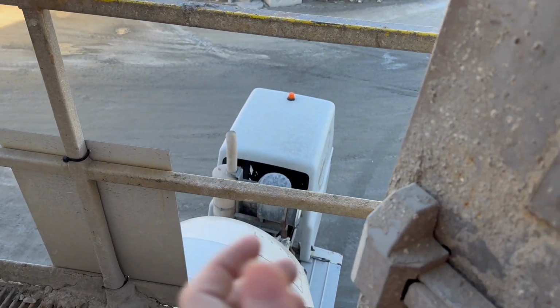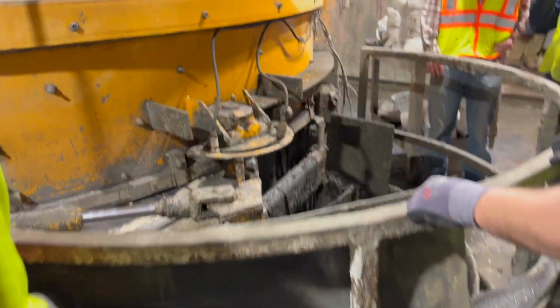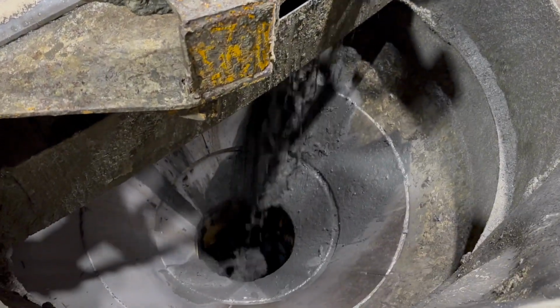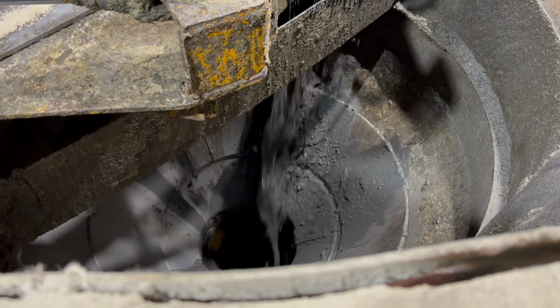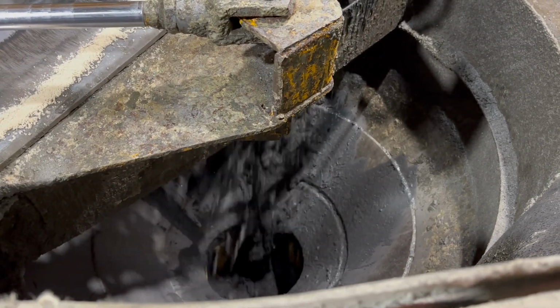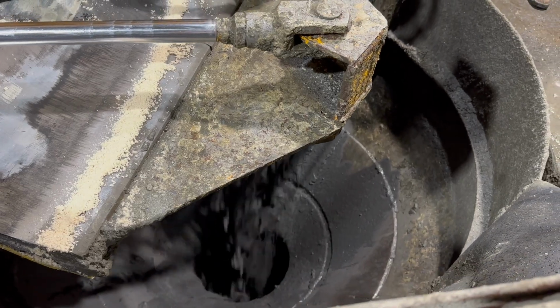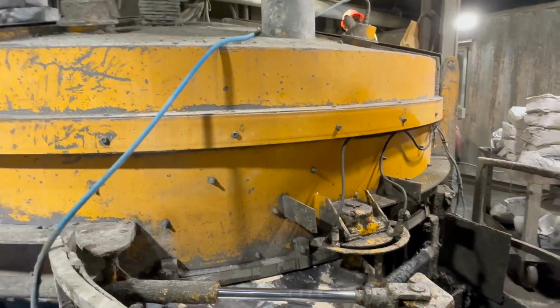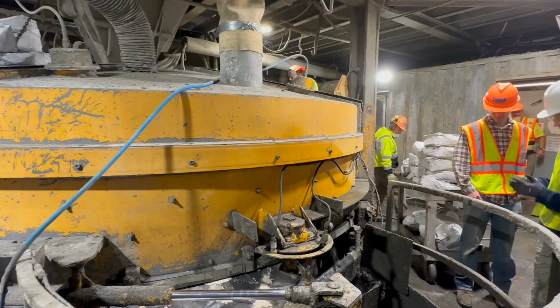Finally, the moment we've all been waiting for, the fibers are added to the mix. All in all, this process took about half an hour, whereas usually a traditional concrete mixture would take the plant less than 5 minutes. This is just because there was a lot of additions that had to be added in by hand, and because these batches are only done about once a year, so the crew was not as experienced with this mix. Also, because the mix was so dry since the water-cement ratio is low, we had to wait a little longer for the mix to become fluid.